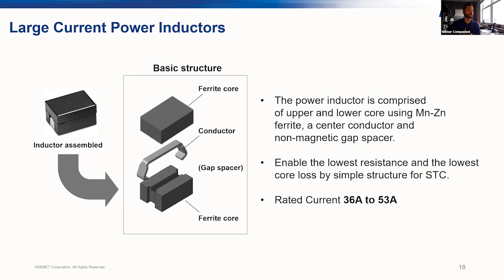Now, what that enables is, because of the relatively high permeability of that ferrite material, you can get a fairly high amount of inductance from that one turn. And what that one turn also does for you is that it has very low DCR. Because if you think of the resistivity equation, which is R equals rho L over A, when you minimize the overall length of the conductor, you minimize the total resistance. So you have a low DCR, which is what enables some of those high currents that I have highlighted there on the screen, 36 up to 53 amps.